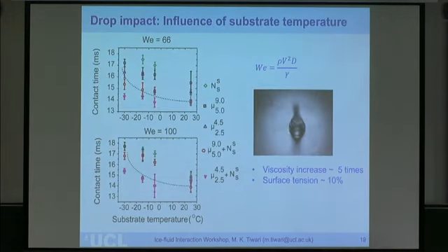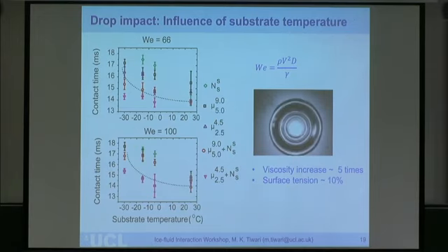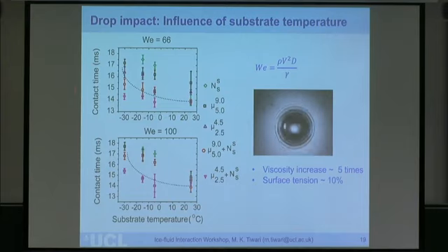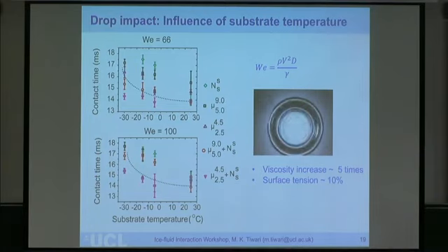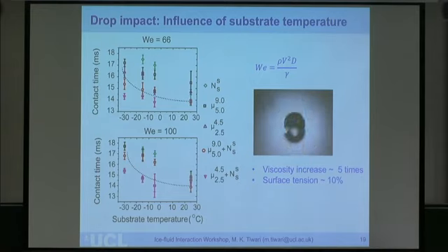And what we see if we do droplet impact experiment on these surfaces is, first of all, so this is trying to plot the amount of time that this impacting droplet is spending on the surface. So it comes down, because of inertia it spreads, then the adhesion between the droplet and the solid is very low because we have made the surfaces to be super hydrophobic, so they recoil back and then take off the surface if the impact speed is low enough. And we can characterize the impact in terms of Weber number. So this is inertia, rho v squared, density times velocity. This is, let's say, the size of the droplet, d, and surface tension again.